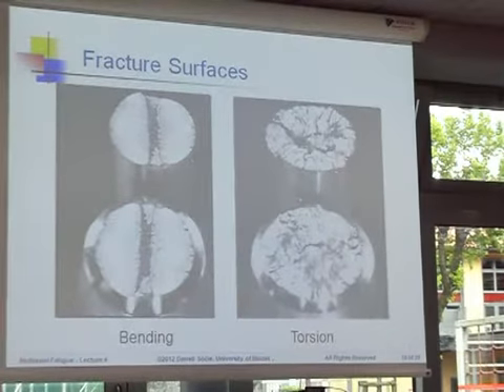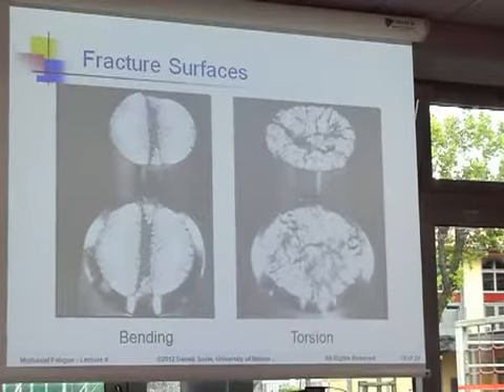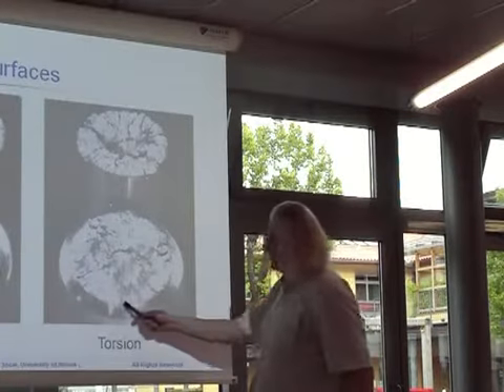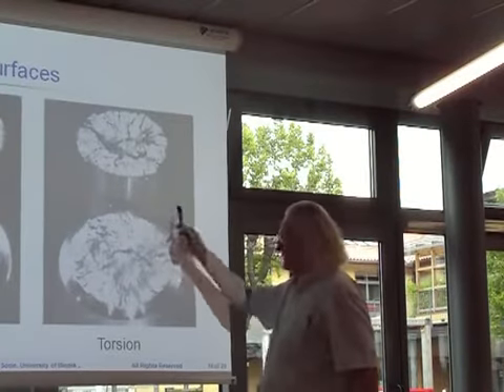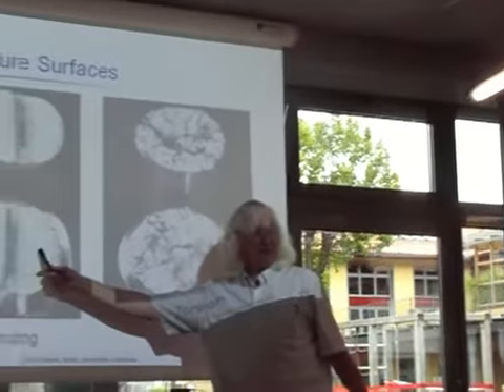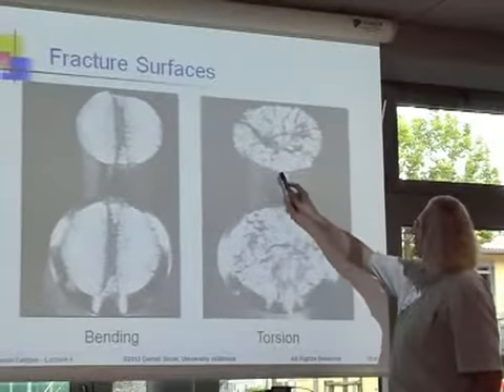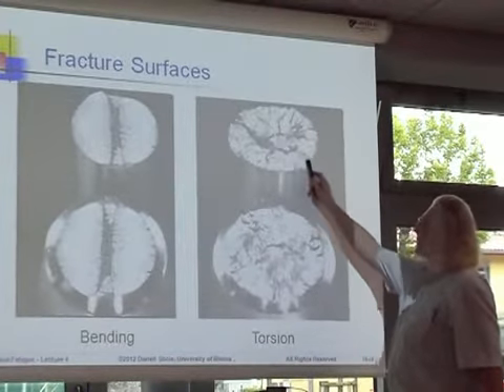Let's look at just twisting this now. I take the same bar that we had in bending and now twist this back and forth. And when you look at the fracture surface, this is what you see. Nothing planar like this. Look how irregular this fracture surface is.